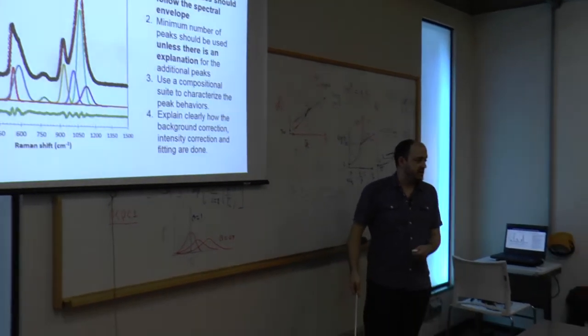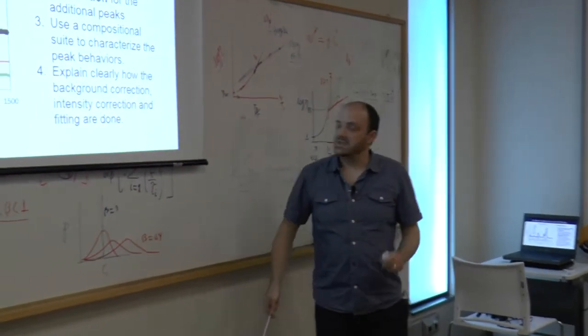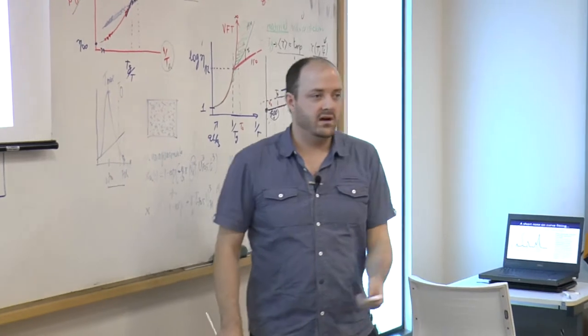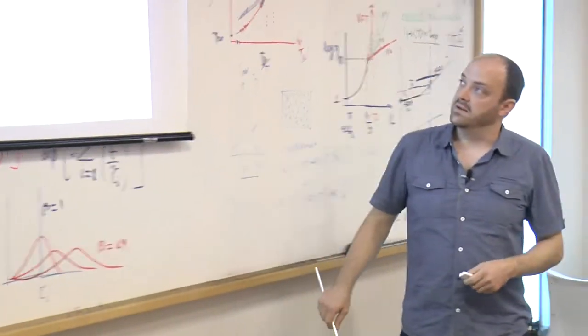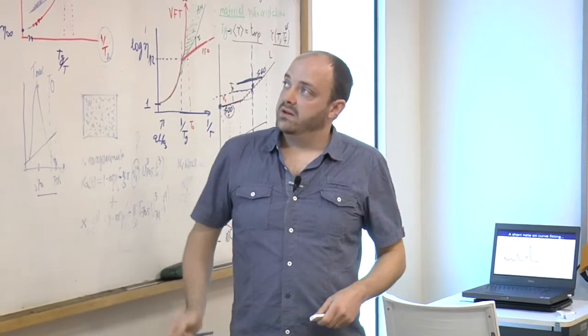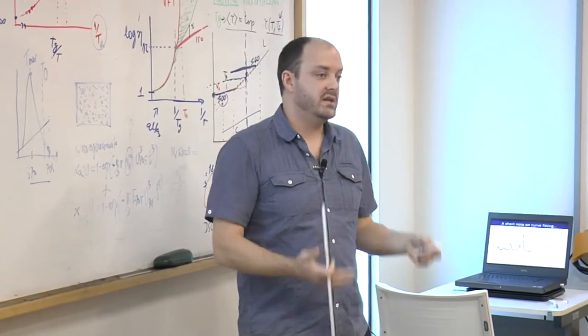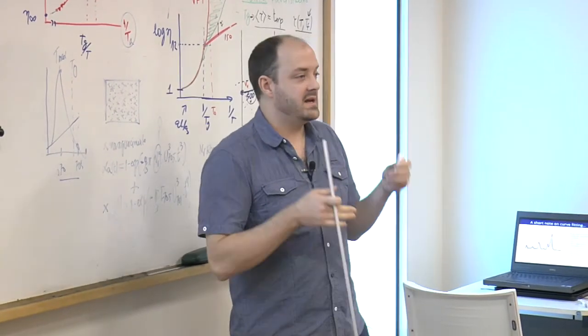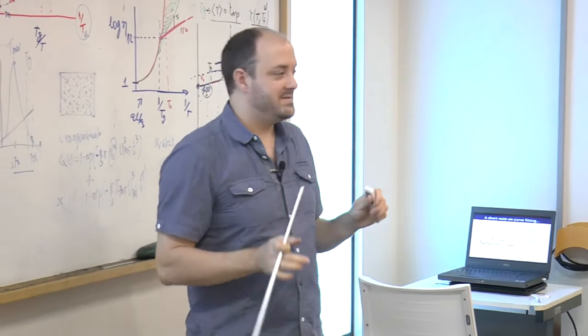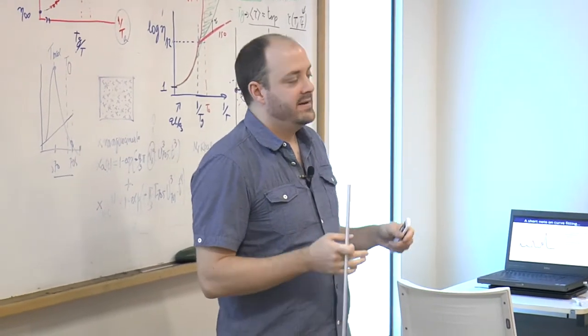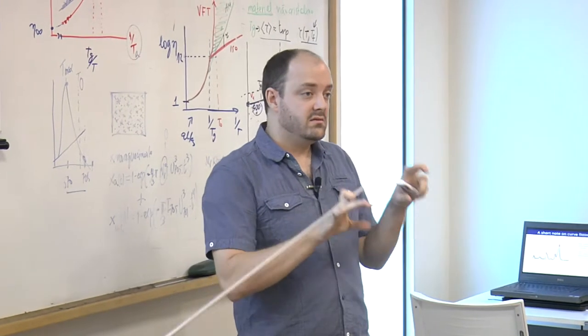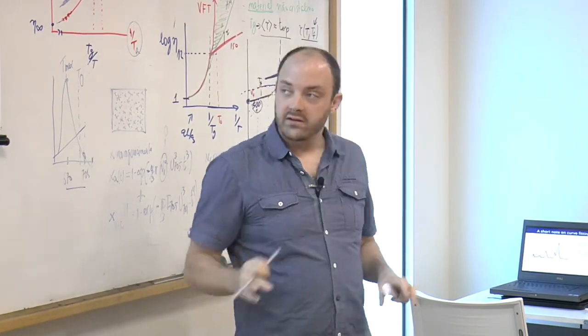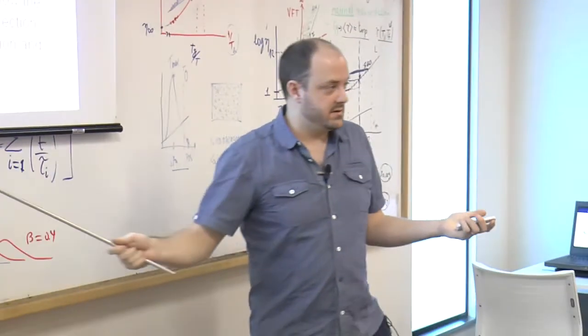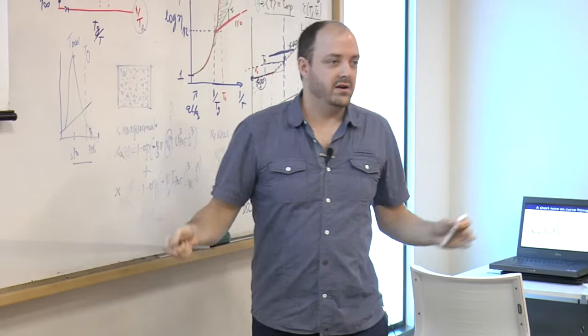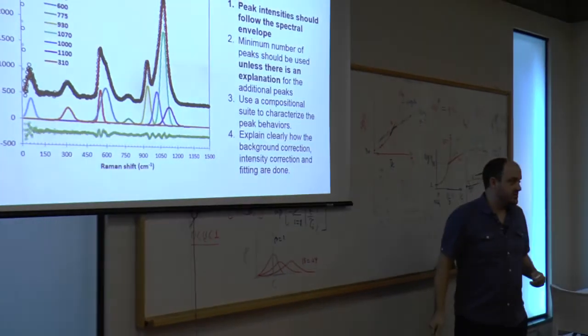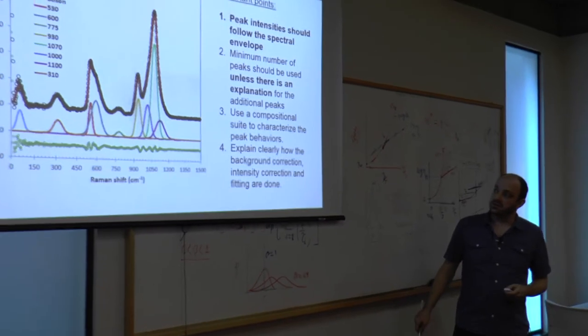If you have little peaks inside of big peaks, then chances are that's just there for the fit, and it's a mathematical fit and not actual conscious thinking of what those bands represent. I always say the minimum number of peaks should be used unless you have an explanation for those additional peaks. There's lots of studies that put peaks in, but then they just add extra peaks to fill in the gaps in their spectra. Oftentimes, a bad fit is one where you don't have an explanation for those extra peaks. Everything that's in here, I have a reasonable explanation for. If you have extra peaks, they're shifting and having an impact on the structural features and will probably change a little bit the interpretation of the spectra.